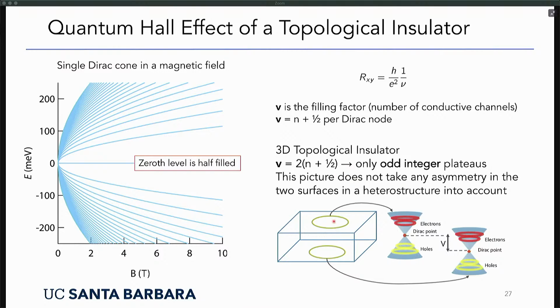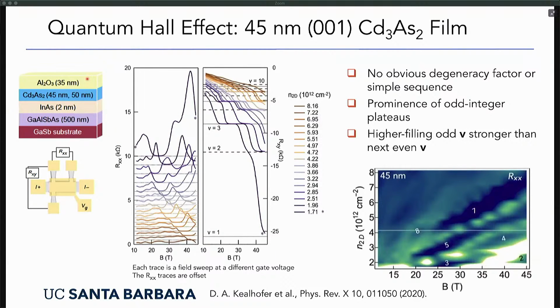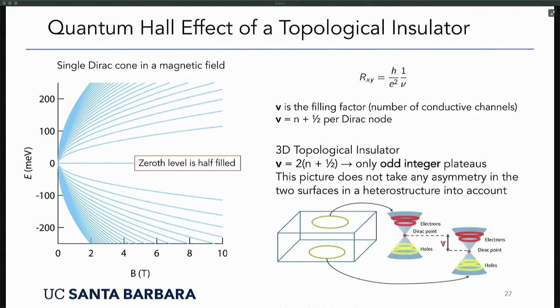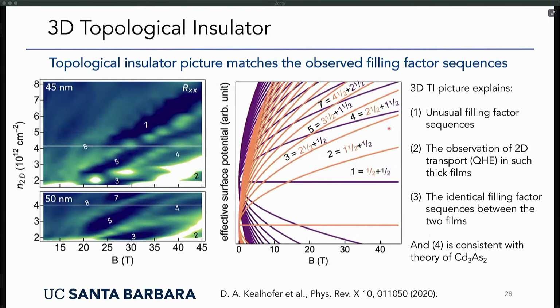But this picture doesn't take into account that we have heterostructures where the two surfaces are not really at the same potential. Okay, so that's what I've indicated here. If you go back, for example, on one side of the heterostructure we have aluminum oxide, on the other side we have the III-V semiconductor. So this is a very asymmetric heterostructure, so it's unlikely that these two Dirac nodes are at the same potential. If you have this potential shift, you get something like what I've shown here. So orange are the Landau levels from one of the surfaces, and purple from the other surface, and you get these intersections and crossings.